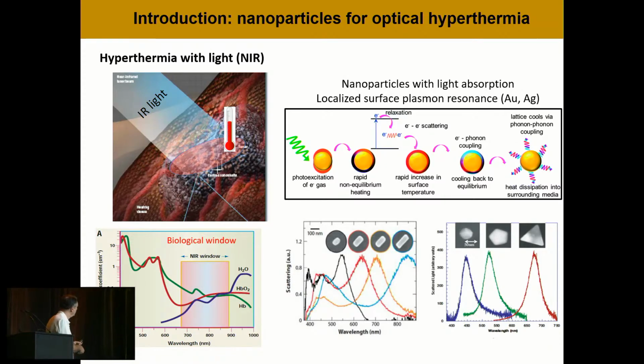And what happens is that this absorbed light has to be released somehow. The way it does is it warms up and releases heat. And we can use this to locally heat the sample. With near-infrared light, we shine a laser somewhere where you have nanoparticles, and we can locally heat that area and not the other areas. Even if the laser is pointed in another place, if there were no nanoparticles, there would be no heating.